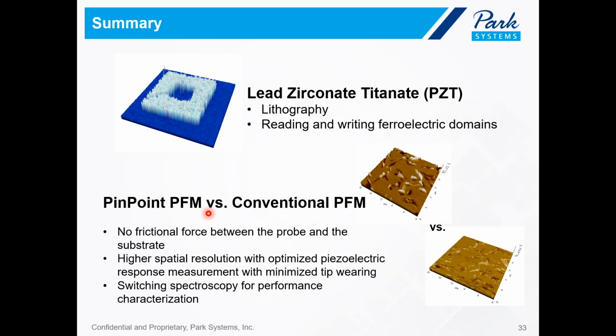The PinPoint PFM mode introduced by Park Systems has proven to offer significantly improved quality in both topography and piezoelectric response measurement. The advanced PinPoint mechanism eliminated the frictional force between the probe and the substrate, enabling concurrent high-resolution topography and piezoelectric response mapping. In addition, the response in strain and polarization as a function of applied voltage was also examined to obtain insights regarding material characteristics such as coercive voltage and hysteresis. So taken in total, PinPoint PFM mode is the ideal approach to characterize localized piezoelectric response at nanoscale with maximized tip life and sample originality as a result of this minimized frictional force between the tip and the sample.